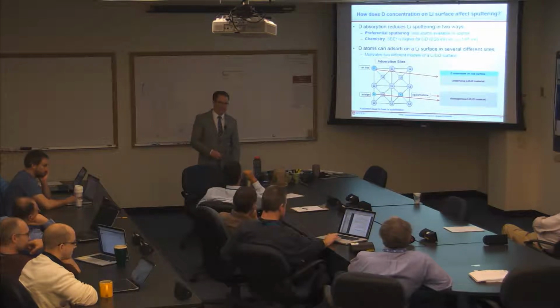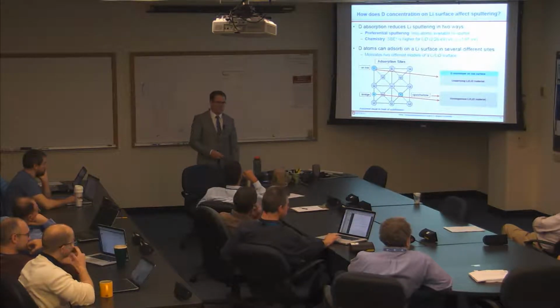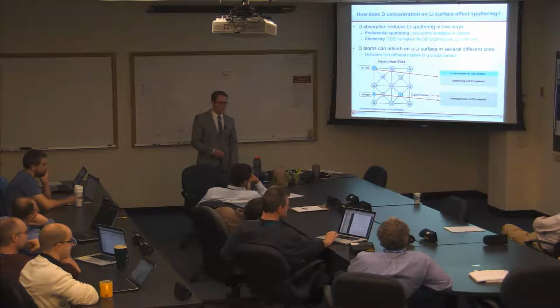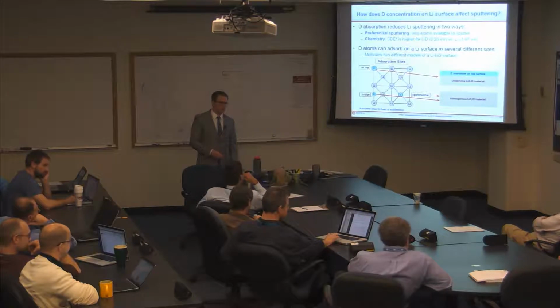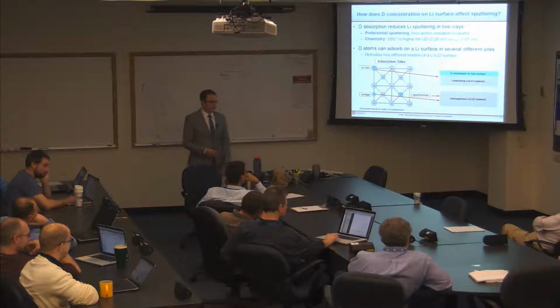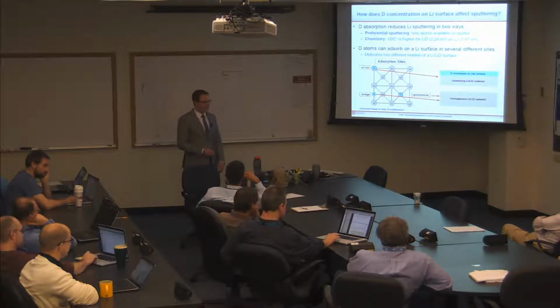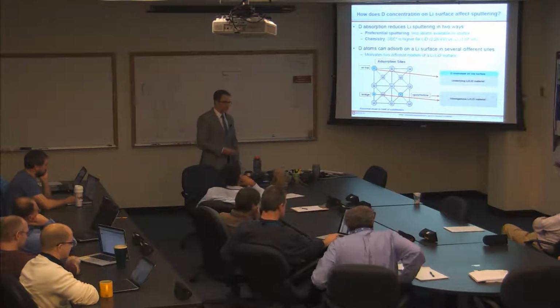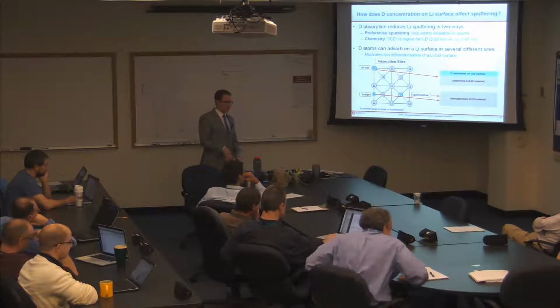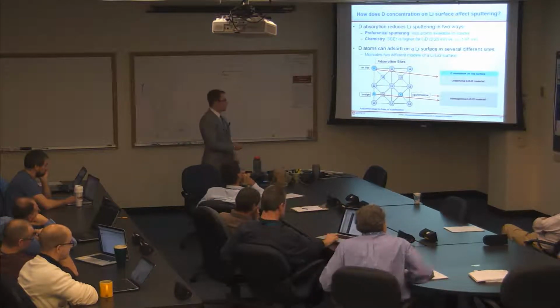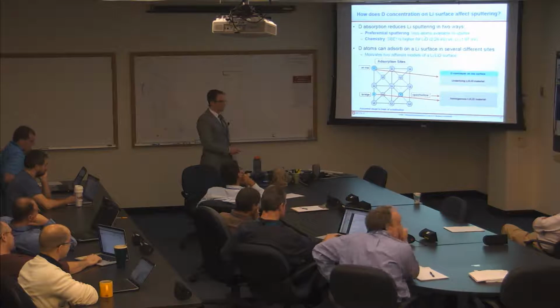Right. So the preferential sputtering is because some of the lithium is kind of hidden underneath the deuterium. It's not the lithium density, it's not lithium atoms being displaced by the deuterium. Right. Yes, that's true. You still have the same amount of lithium. It's just you now also are introducing deuterium. And in this case, the deuterium is actually shielding the lithium to some extent.